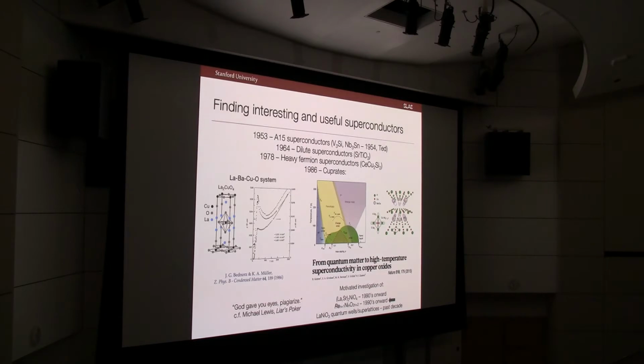The degrees of freedom that are clear are that the electron correlations are in a fundamentally different strong regime. And questions arise about how those interaction effects may manifest different channels of pairing, such as via spin fluctuations, via stripe instabilities, maybe bootstrapping off of electron-phonon coupling. It's a very strongly coupled problem. In terms of the materials, there are probably hundreds of different cuprates nowadays known. They all share a common structural motif, by and large, of being composed of CuO2 planes. So it's a quasi-two-dimensional crystal structure with different sequences of stacking of these planes, in their proximity and different interspacing layers.